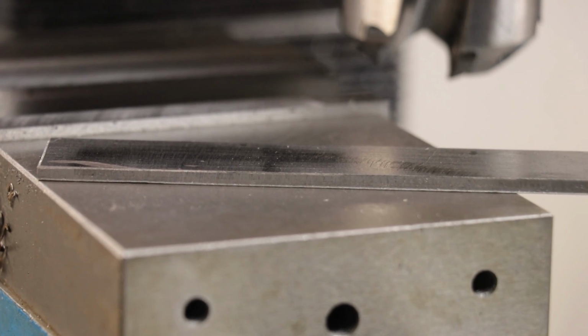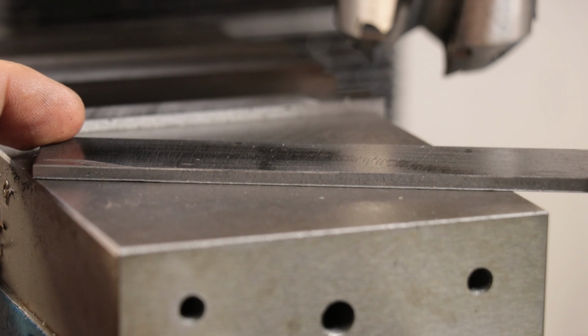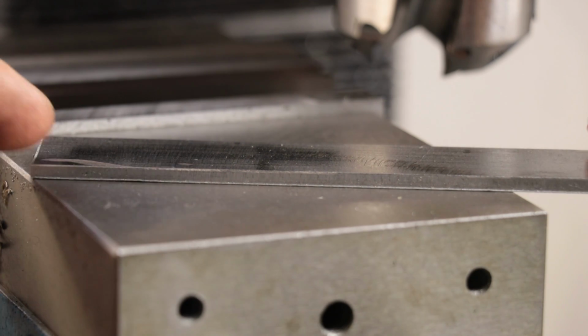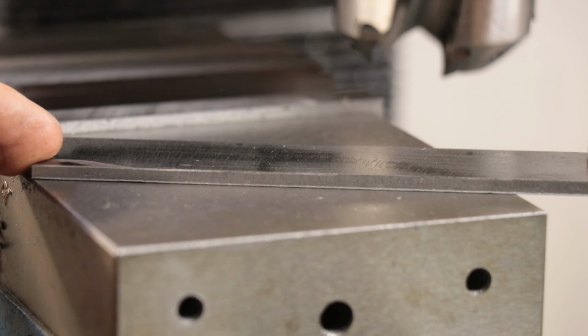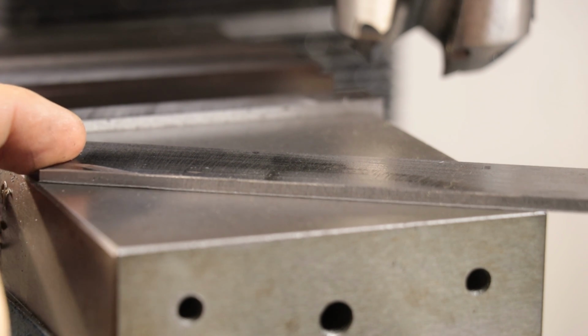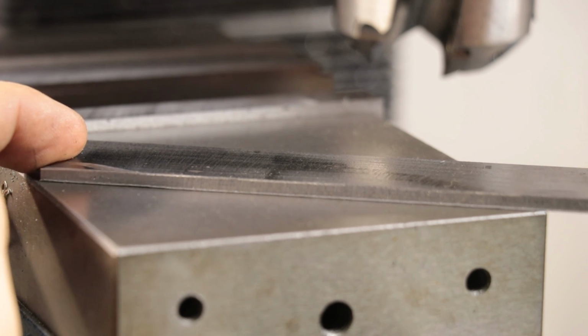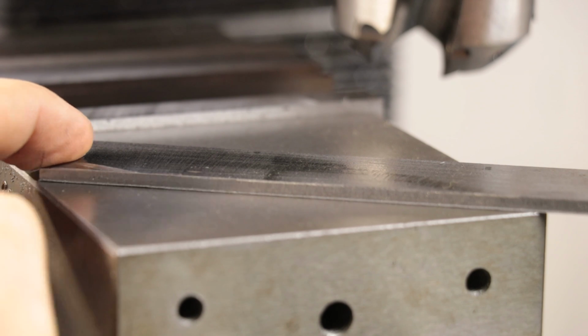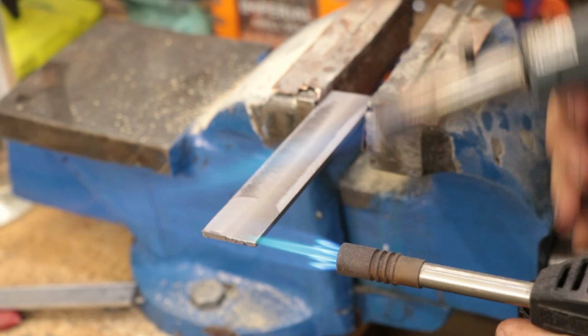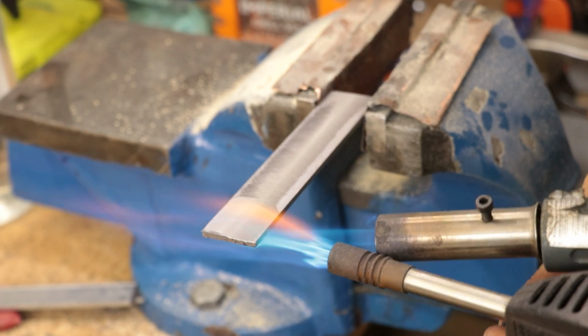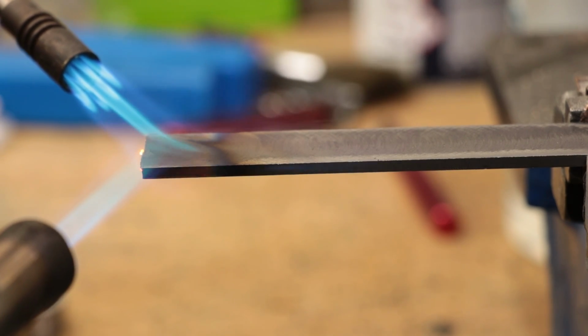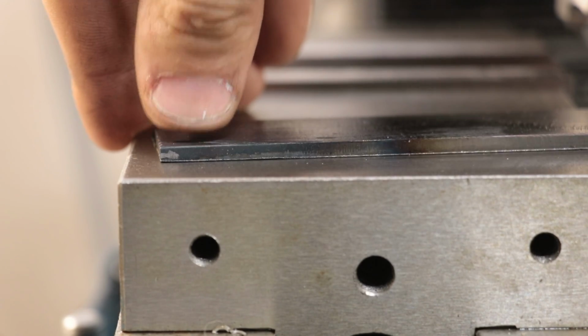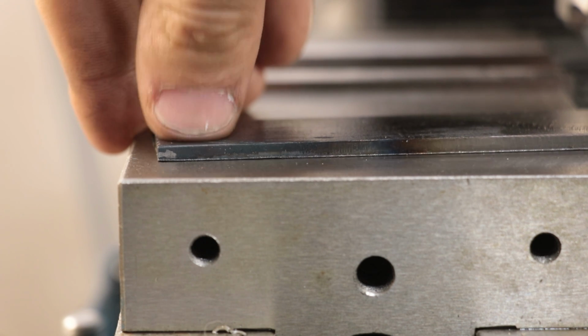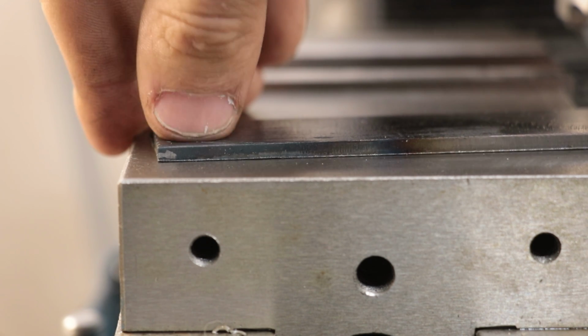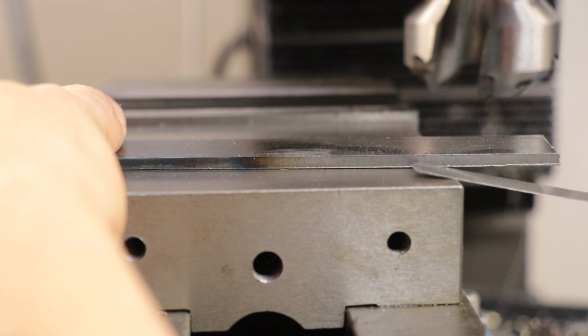Now, as you can see here, it's not a whole lot. I could only fit, say, a 10 micron shim underneath it, but at the end of the day, that's still 10 microns too much, and depending on the tolerances of the part and the drawing, that could easily amount to a scrapped part. Now, if we further heat or unevenly heat it, we can cause it to warp even further. It probably doesn't look like a whole lot more on camera, but I can now fit a 15 micron shim underneath it.